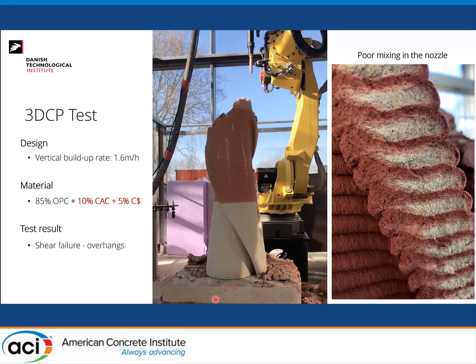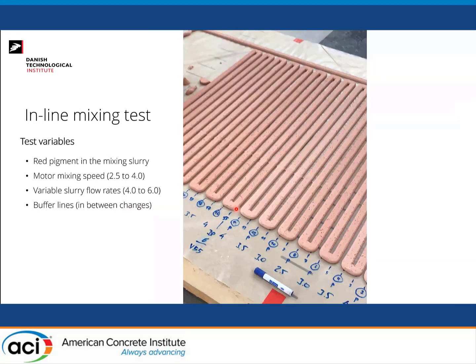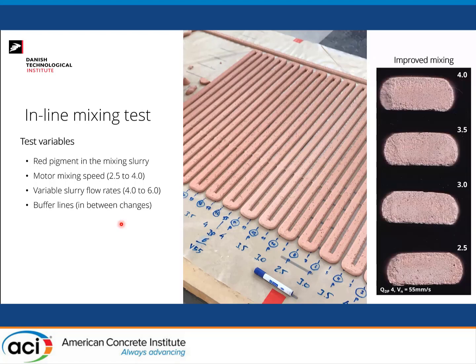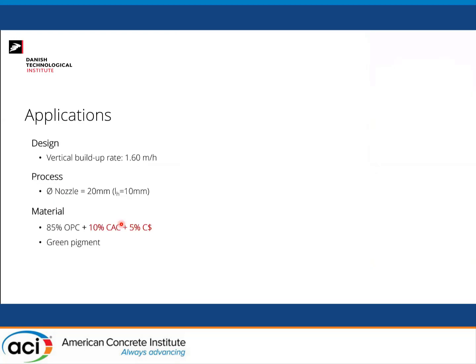And you see, for architecture applications, I don't have to go too much into details here, but for the first few layers we didn't add any pigment, and then later on we had some pigment. So we identified that problem with the inline mixing test, and then we ran a few more experiments varying motor mixing speed and the flow rates that we're injecting. By tuning the system a bit and changing the mixing shaft, we could have an improved mixing. So we guaranteed that, and say that one is checked.